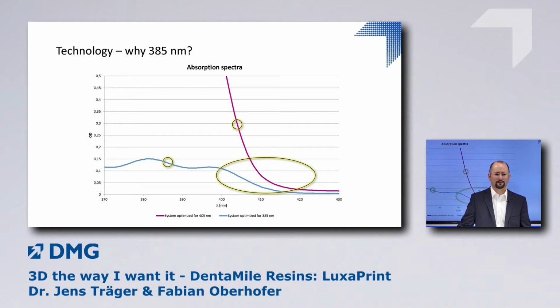We remember that this is a range where the human eye is still able to perceive color. And the absorption of our 385 nanometer material is remarkably less than that of the 405 nanometer material, especially here in the range between 400 and 410 nanometers. What this means is that the 405 nanometer optimized material absorbs or extracts more blue light out of the visible spectrum than the 385 nanometer material does. And what happens is that we see the complementary color of blue, which is yellow.